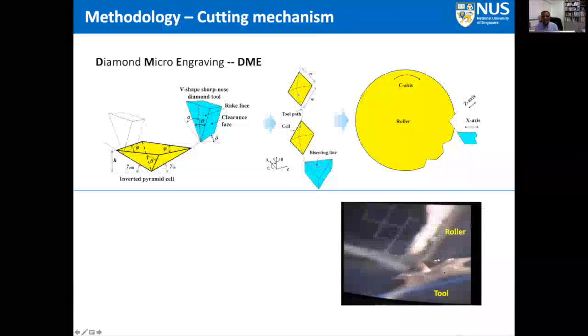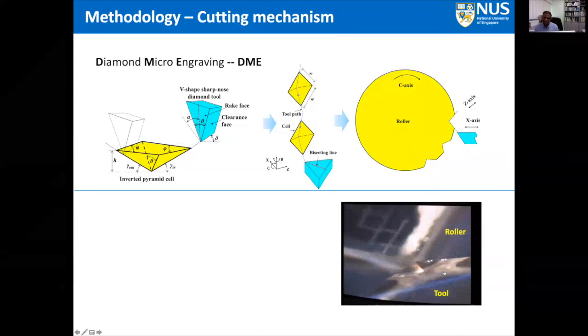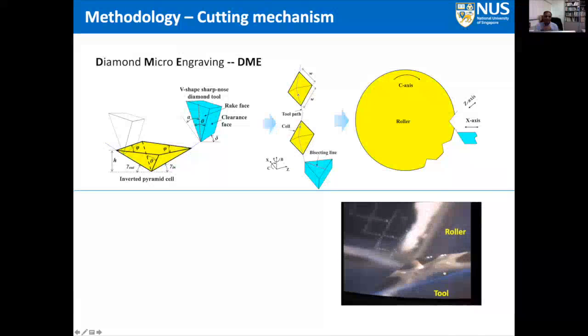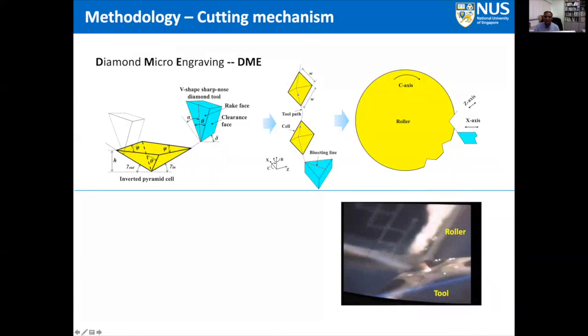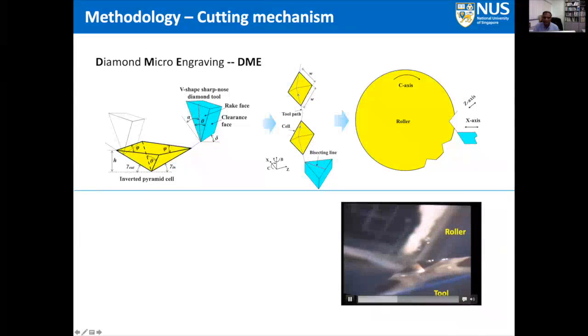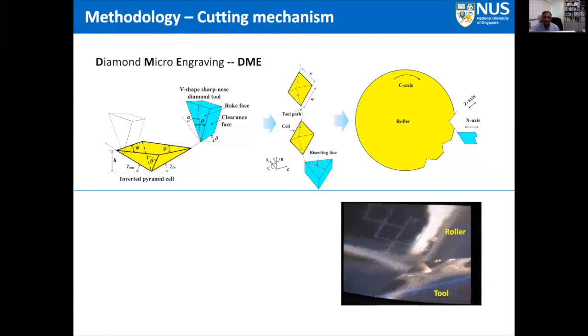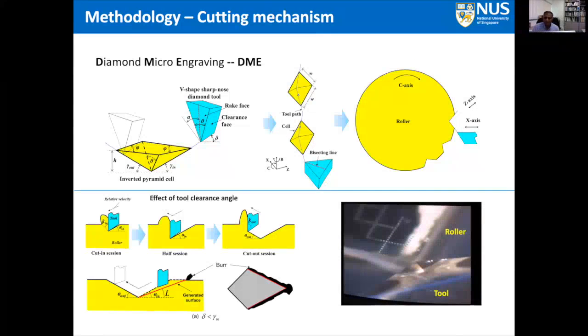So how do we go about doing it? This is done with the help of a diamond micro engraving technique, which I mentioned to you earlier, where when we wanted to machine the Einstein image, we did the same process. What you see here on the image at the bottom is a video where you can see the cutting tool moving forward and backward in order to create this kind of diamond micro engraving. How this happens is that the cutting tool enters here in the beginning, goes down all the way, and then it is chiseled out by moving away, and then you can produce a very interesting V kind of pyramid structure.